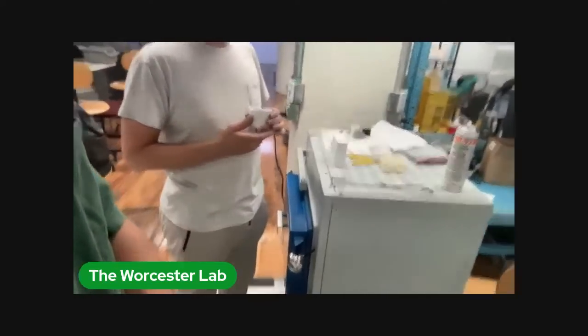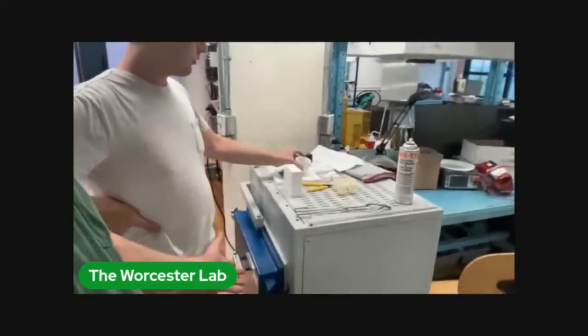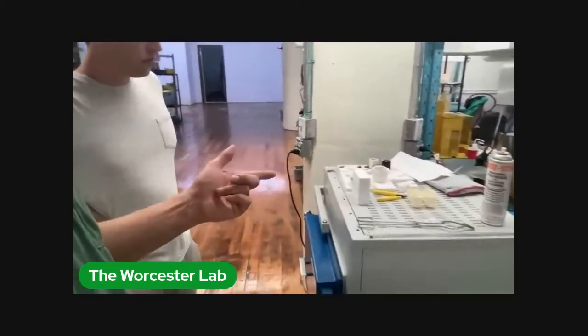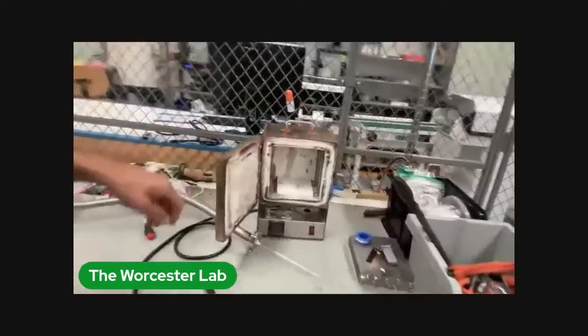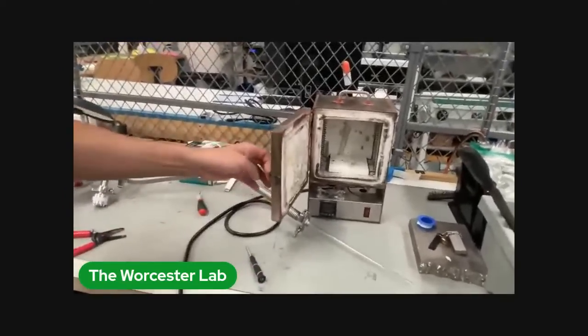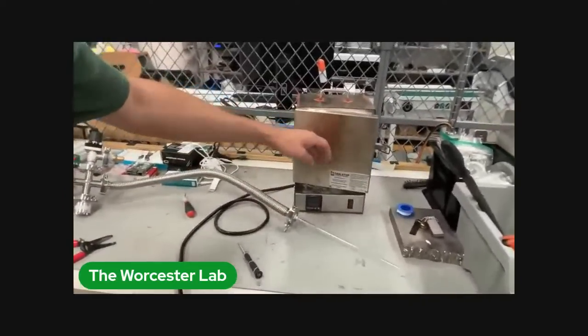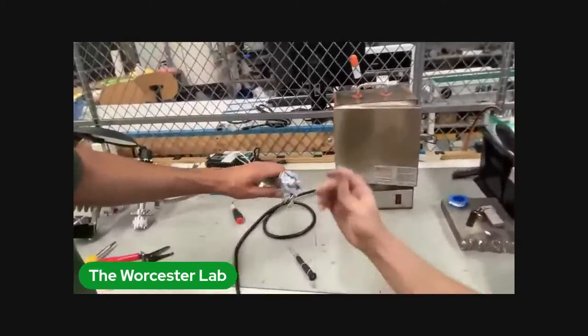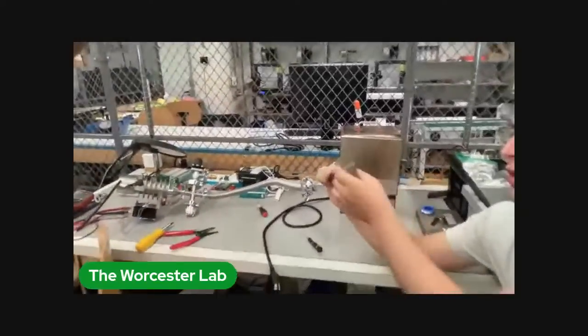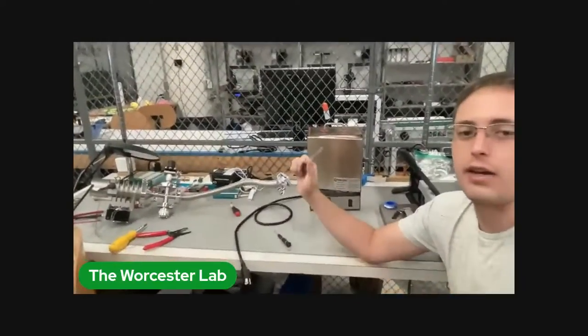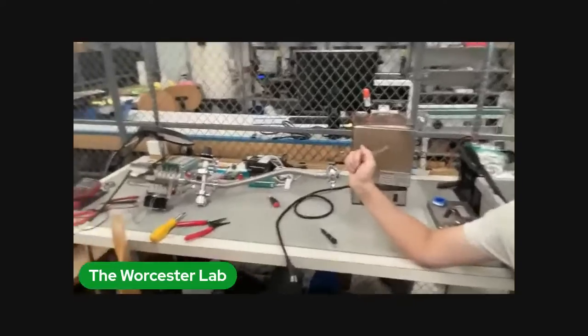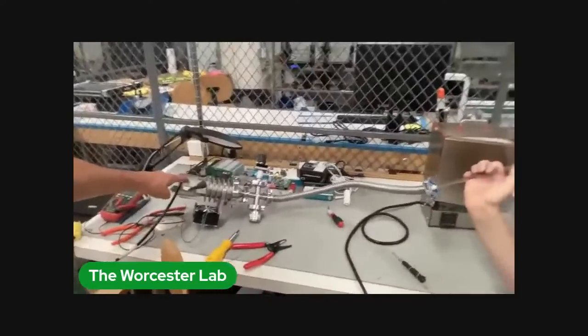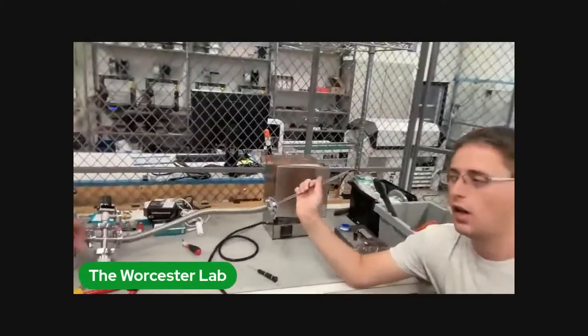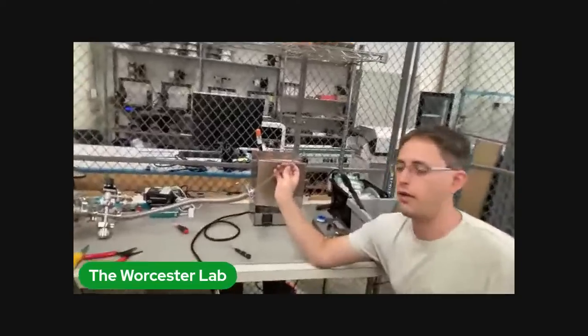And what about the vacuum? They did a process with this vacuum tube, like over here, where we had been set up to do this in a smaller furnace. If you didn't have a vacuum furnace, that's an $8,000 furnace over there. So, yeah, if you can pull vacuum on a quartz or borosilicate glass tube, then you can blowtorch ampules off of that and fill them with material, and then you can put it in a normal furnace and try the same experiment. It works well enough.